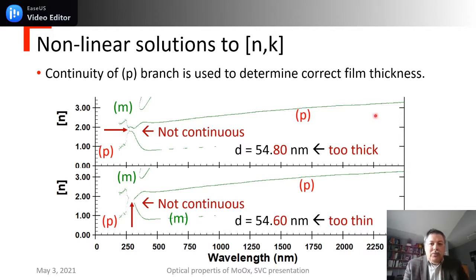What happens if you use a thickness in your solution that is too thick? The P branch over here is nice, and all of a sudden it breaks apart over here. It's not continuous. On the other hand, if it's too thin, it breaks apart in another way. And you can see that this difference of 54.8 and 54.6, a difference of 0.2 nanometers, we know that this is incorrect. So previously we mentioned that the correct thickness was about 54.7 nanometers. And we are quite certain of that because of the continuity of the P branch.